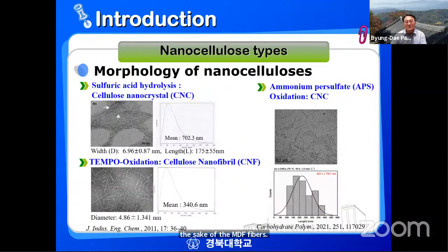You have different methods to isolate cellulose. When you have cellulose nanocrystals, you can get them using sulfuric acid, diluted to about 64%. And then you have these whiskers. They have very pointed ends, a little bit thick at the middle, and the diameter is about 7 nanometers and the length is 175 nanometers. This is a wet analysis. The mean, the length and diameter together, is about 700 nanometers.